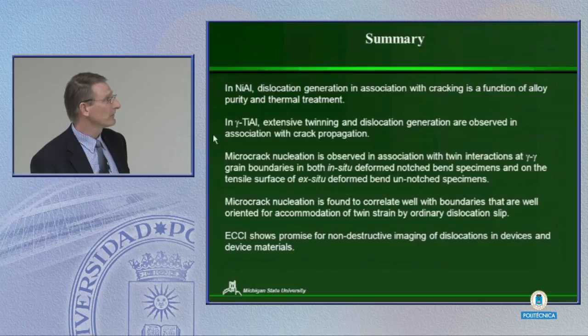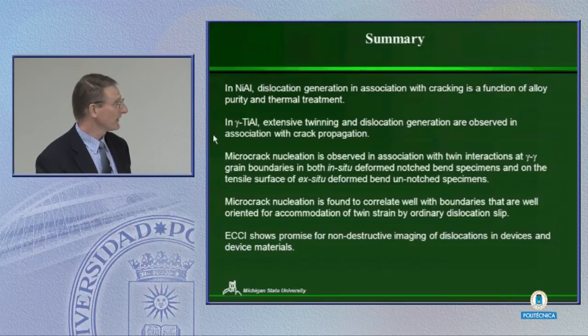We have bulk samples, more representative in terms of their state of stress. We have a large SEM chamber, so it gives us a lot of options. We can actually now do this at, we haven't imaged dislocations yet, but we can certainly do in-situ experiments up to 900 degrees C with straining.